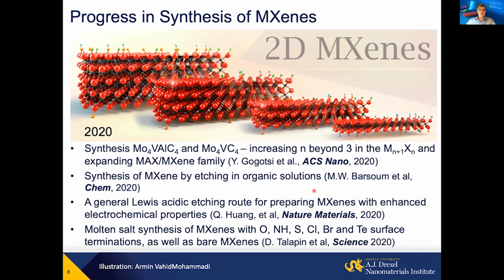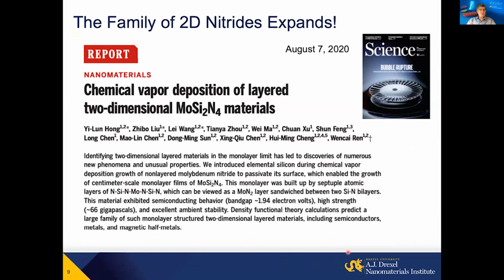Synthesis of MXenes by etching in organic solutions was shown by Professor Barsoum's group. A new general Lewis acidic etching route for preparing MXene was proposed by Qing Huang from Ningbo. And I just showed you the paper from Dmitry Talapin on a variety of surface terminations here. And the system of carbides and nitrides in 2D can grow further. Hui-Ming Cheng, who already talked at this conference, and Wencai Ren from the Institute of Metal Research in China, published in Science about a month ago, a little bit more, August 7th, a paper on CVD synthesis of molybdenum nitride, which is not exactly the MXene structure, but again, two-dimensional nitrides here.